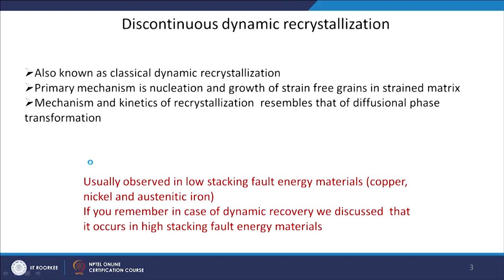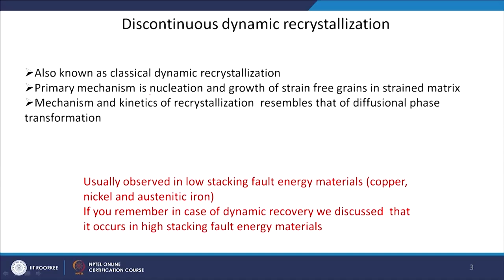If we look at discontinuous dynamic recrystallization, sometimes you will also know it as the classical model or classical dynamic recrystallization. The main important characteristic of this kind of recrystallization is that it occurs through nucleation and growth. Recrystallization means a new strain-free grain will grow in a deformed matrix. When we apply deformation, dislocations are introduced and dislocation density increases in the material, so the strain energy is increasing in the material and the material wants to bring down its free energy.